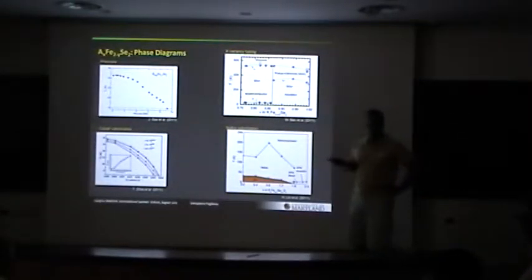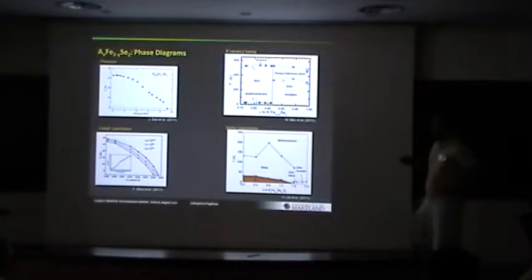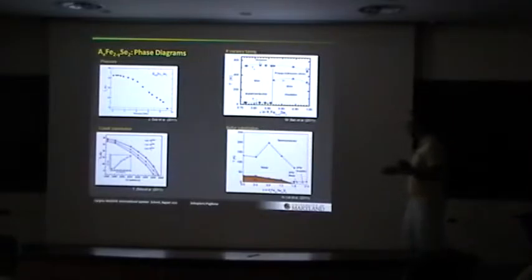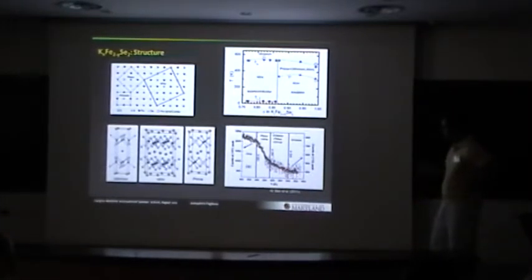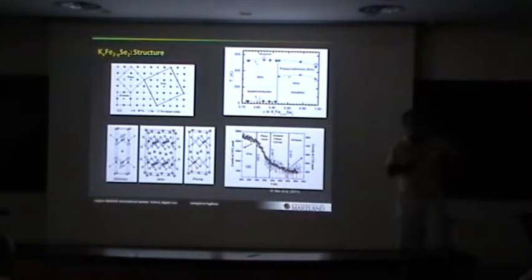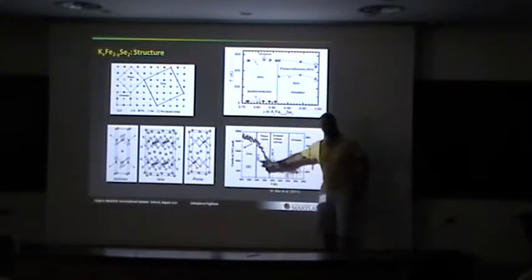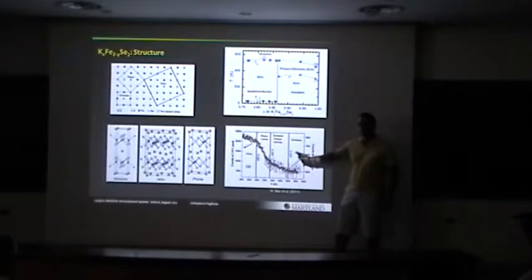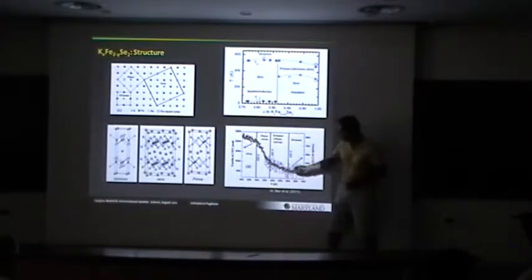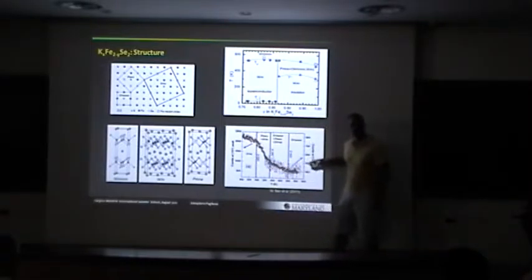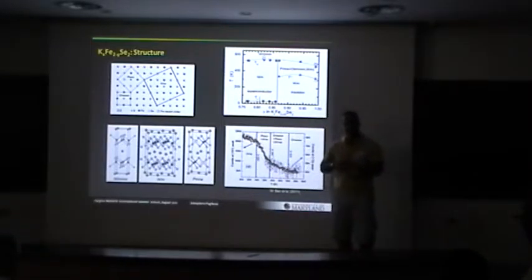So just to show you a few other details on experimental results. If you apply pressure to this superconductor, Tc goes down. Now again, one disclaimer is that I think a lot of these things may be very dependent on the chemistry. Oh, and I forgot one thing. If I go back to, for instance, this behavior here, looking at the different structural and magnetic transitions as a function of temperature, I've also been told that depending on the thermal history of the sample, this can also change. So not only the chemistry, but the thermal history, whether you quench this, whether you heat it up slowly, you anneal the sample, that can also affect the vacancy order, as you might expect.